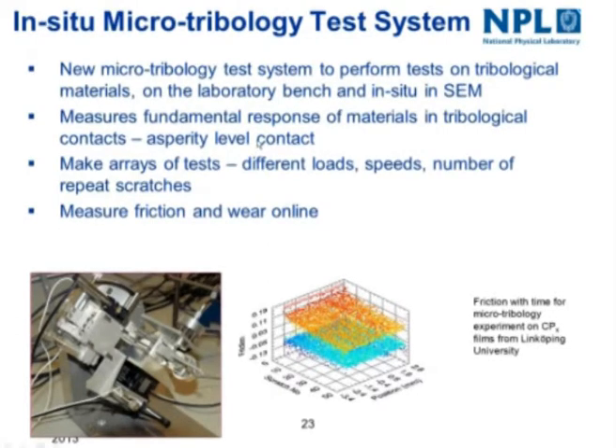I just wanted to mention also that we're doing some experiments with a tribology test system. That's down here. This was developed here at NPL. We carry out experiments on the laboratory bench. I say in situ in the SEM. That's the intention. We haven't got there with that yet. The reason we're doing that is twofold. One is that it's appropriate for MEMS devices, but mainly from our point of view, it's so that we can look at the fundamental response of materials and tribological contacts at the asperity level. We make arrays of tests, with different loads, speeds, and numbers of repeat scratches, and we measure friction and wear when we do that. This just shows an example of the progression of friction on experimental coatings of carbon phosphide from Linköping University.